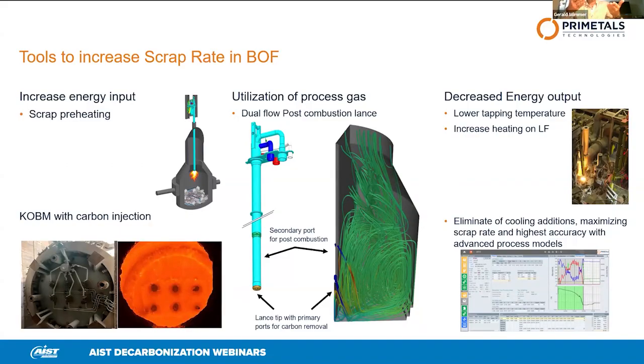If the scrap is hot, of course, it takes less energy for melting later during the process. And as a consequence, you can melt more scrap with the energy available in the hot metal. In the converter, we combust carbon, but not very efficiently. We just combust it to CO. That's why the converter off-gas has high calorific value and is collected and used in the gas holder.